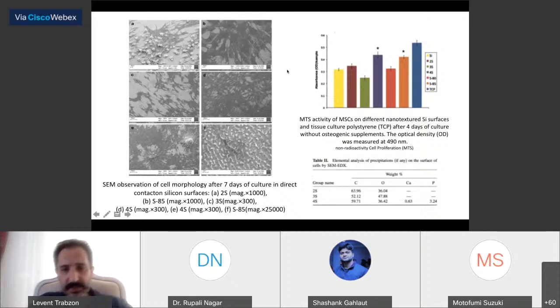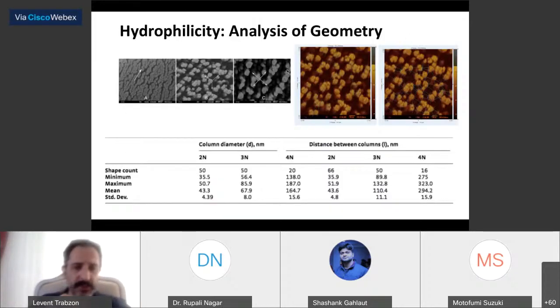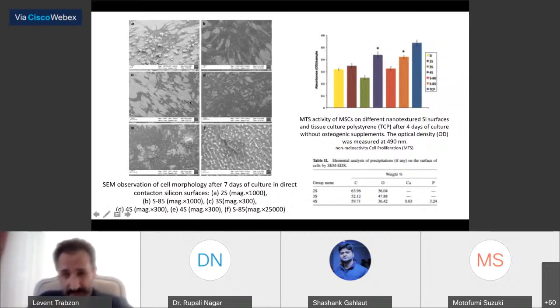So what we have done, we have grown mesenchymal stem cells on such silicon surfaces. On the left-hand side, as you see, these are the observations of the cell morphology after 7 days of culture in direct contact on silicon surfaces. But in all cases, we haven't utilized any growth factors. There is nothing enhancing or moderating the growth in those cultures. And as you see from A to F, there is a very different behavior of the mesenchymal stem cells on different nanotopographies.